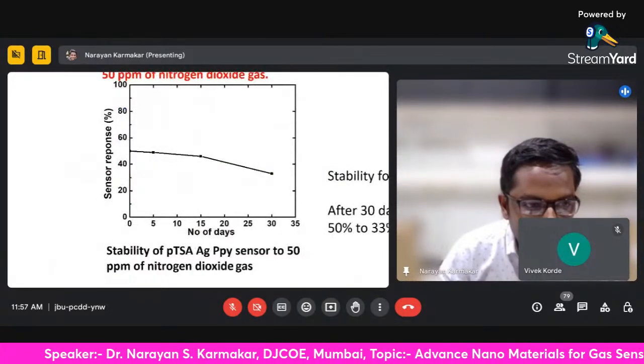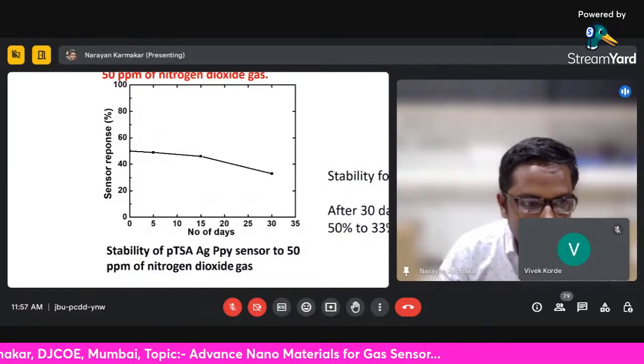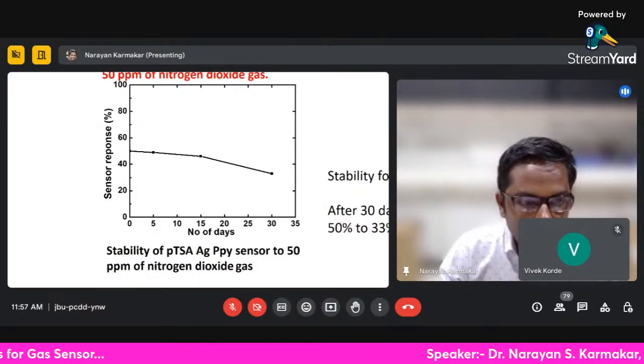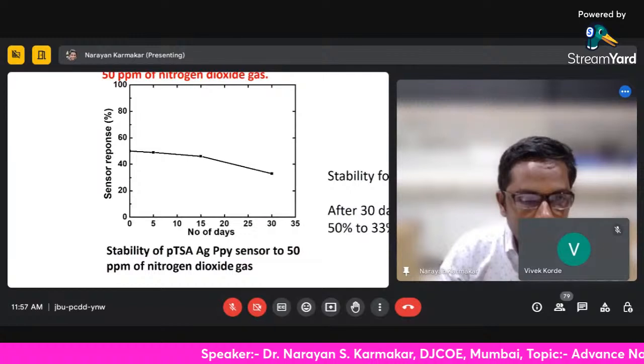Also, we studied the stability of this gas sensor. Initially the sensor response was about 50% for 50 ppm gases, and over a period of 30 days the sensor response decreased to about 33%.